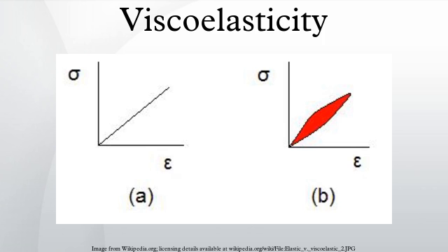First, an elastic component occurs instantaneously, corresponding to the spring, and relaxes immediately upon release of the stress. The second is a viscous component that grows with time as long as the stress is applied. The Maxwell model predicts that stress decays exponentially with time, which is accurate for most polymers. One limitation of this model is that it does not predict creep accurately.